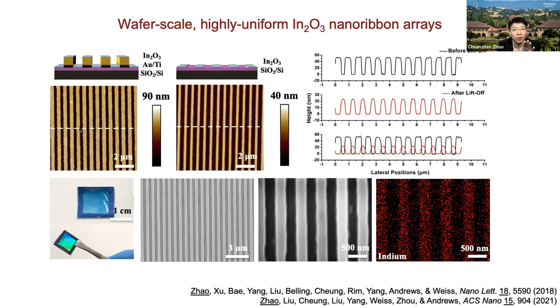Okay, so actually, the size is not even at the beginning, and this is due to when I put the PDMS to the CD. You have a very good eye to catch that. The pitch size is set around 700, but the size is a little bit tiny here if you fit in the PDMS stamps, and that's why I took this AFM profile to match them and see if they fit very well. So that's the thing that is a little bit off, I would say: when you put the PDMS into the mold and take it off, the size is going to change a little bit. That's not from the patterning process, because those can fit the tiny one and a slightly larger one. This is more apparent here, but actually it's a similar process, because I checked the profile.